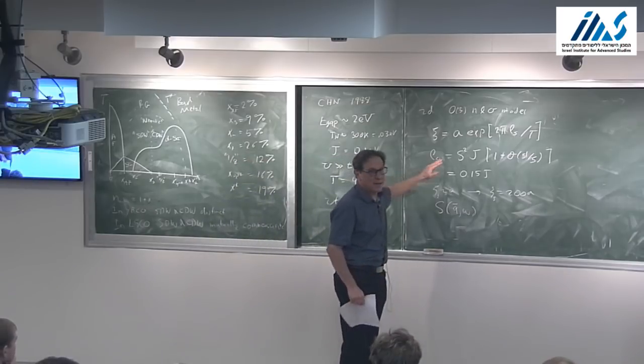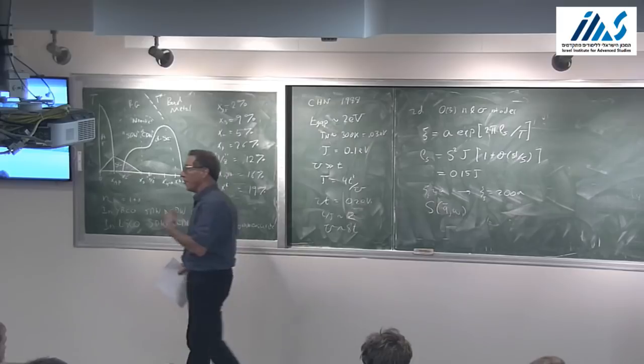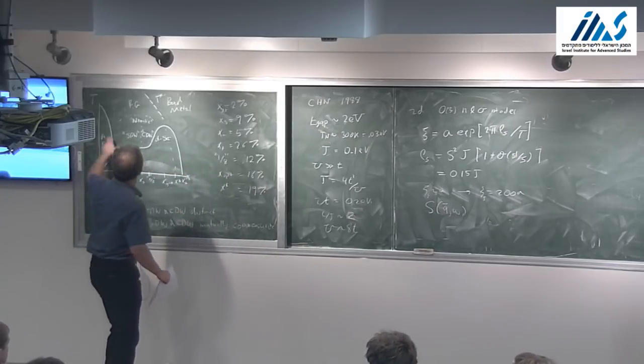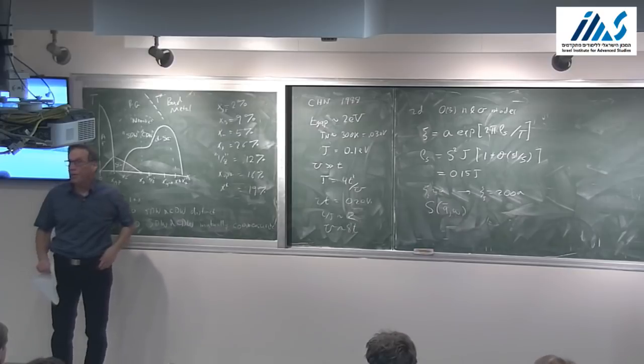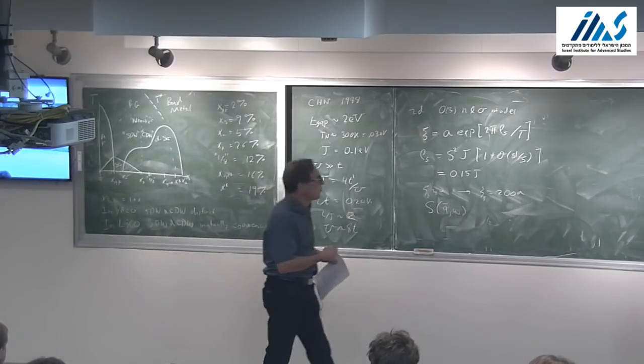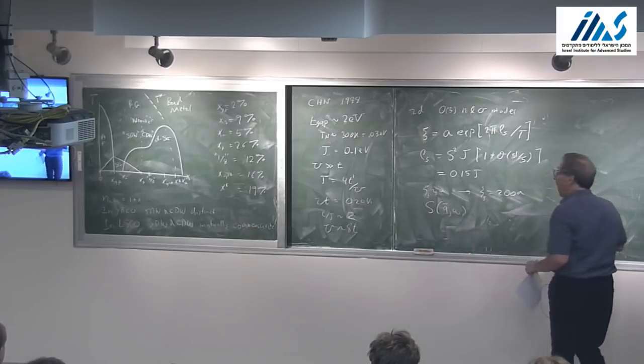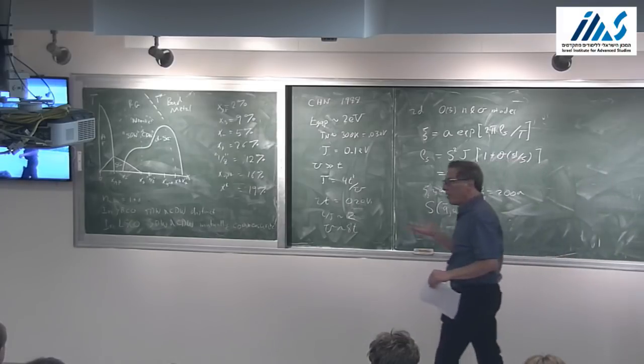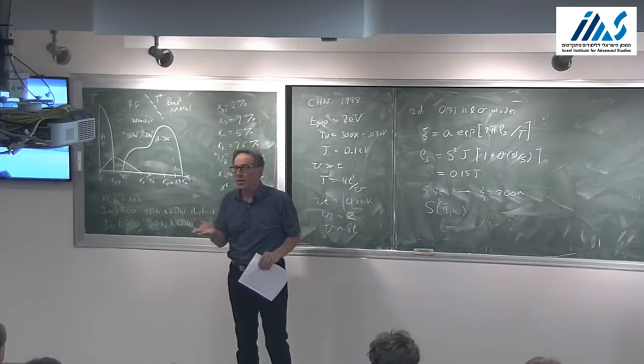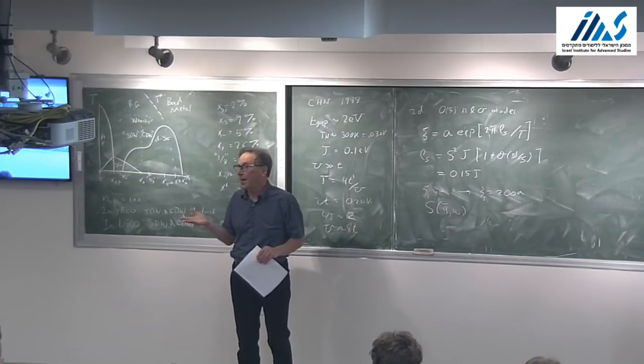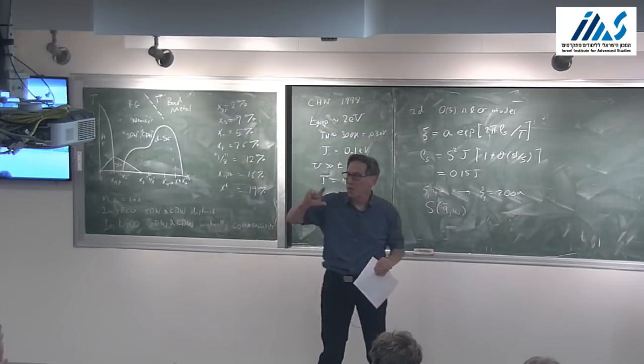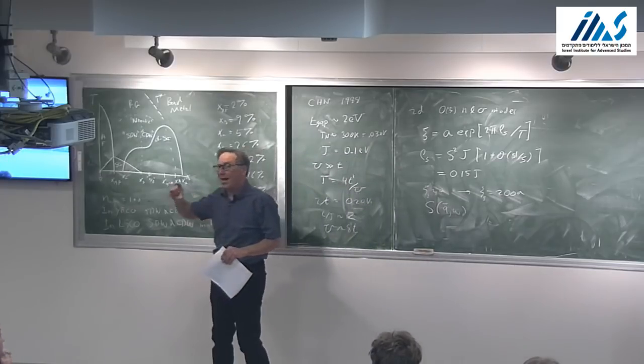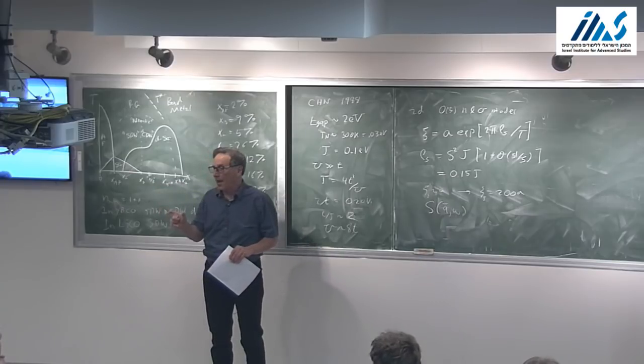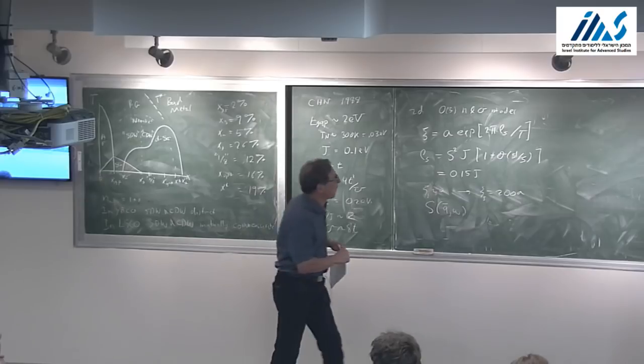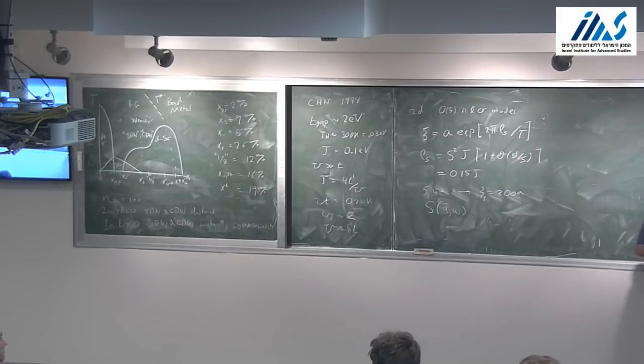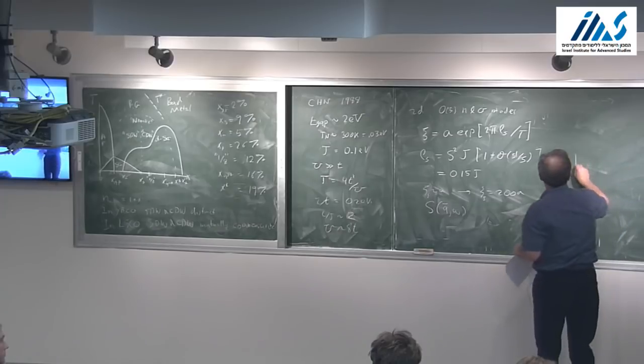Okay, so here, this is the two-dimensional theory. The two-dimensional theory, of course, doesn't order. You would like to understand the physics of the Néel temperature. The physics of the Néel temperature can also be understood very simply. The cuprates are very layered, so the coupling between nearest neighbor planes is much smaller than the coupling in planes. In fact, the J between nearest neighbor planes is something like 10 to the minus 3 of the J within a plane.